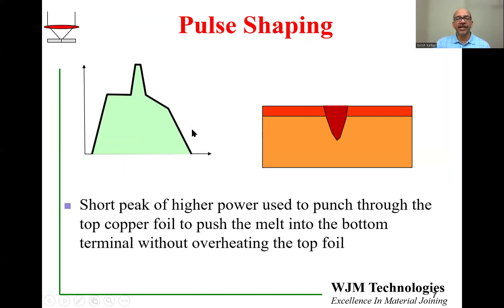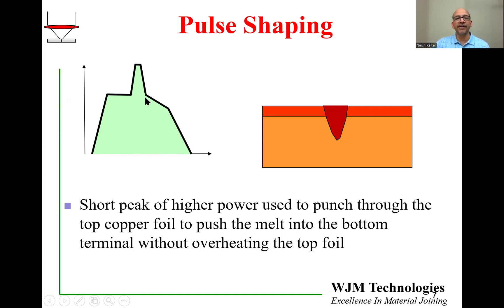Pulse shaping can take different forms. One type I used involved a pulse shape with a small spike in the middle. This was necessary for welding copper because we needed a very high peak power, but if the time at very high peak power was too long we ended up with drilling and spatter. So we kept this sharp spike to a very short time on the order of half a millisecond, which helped push the copper metal into the copper alloy below to make the weld.